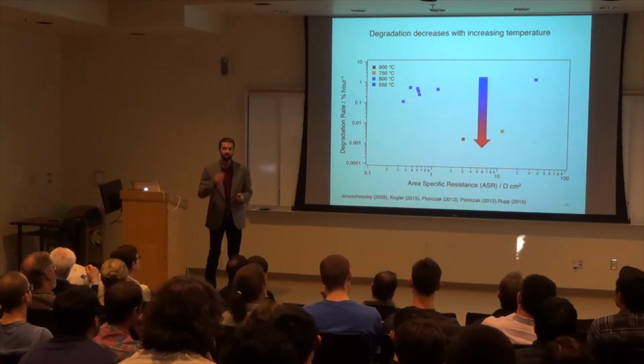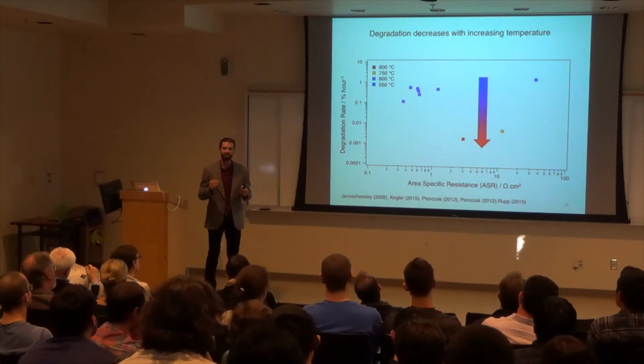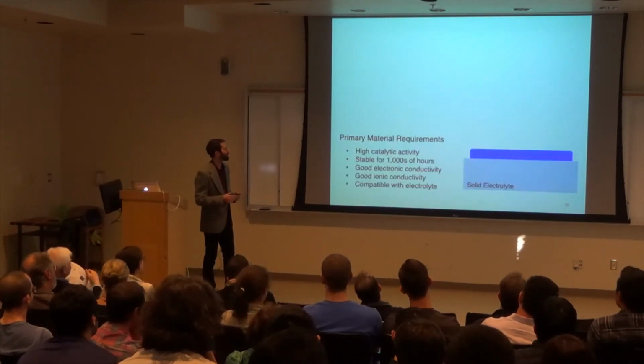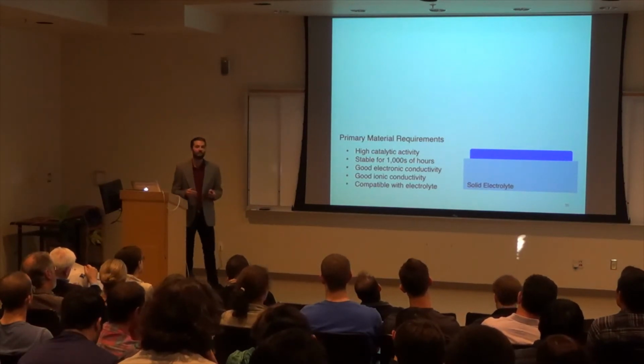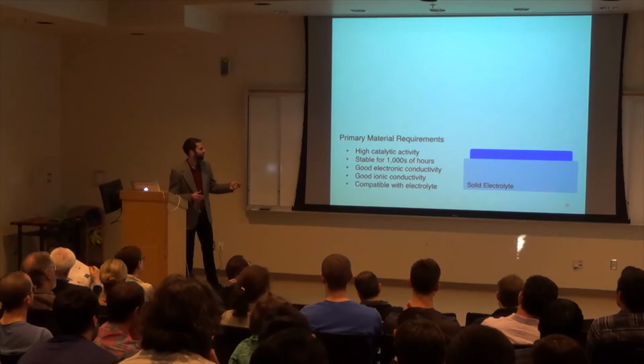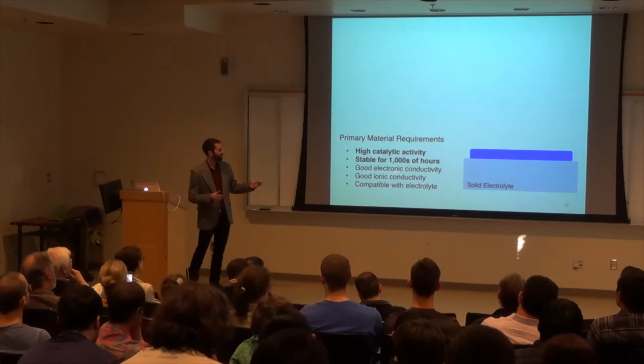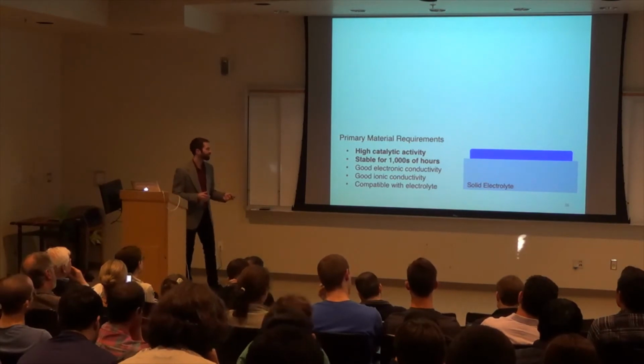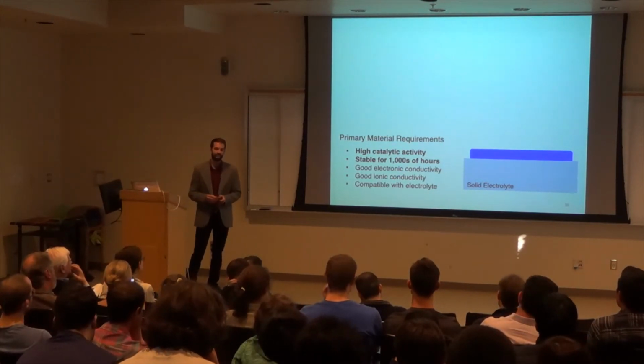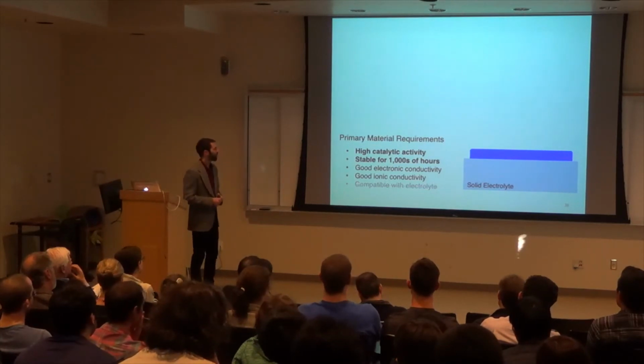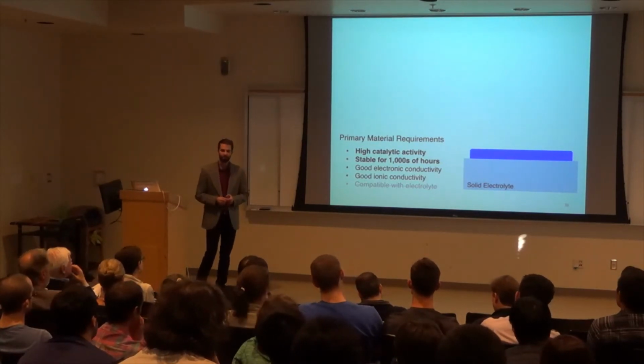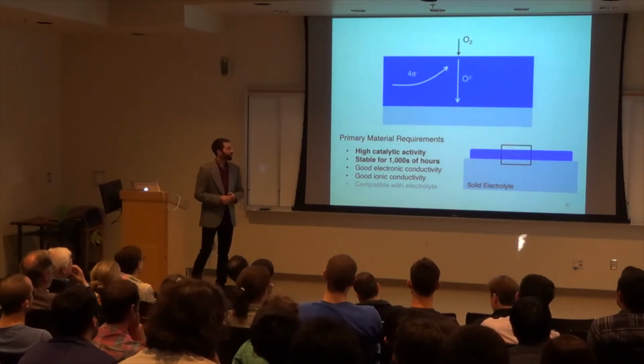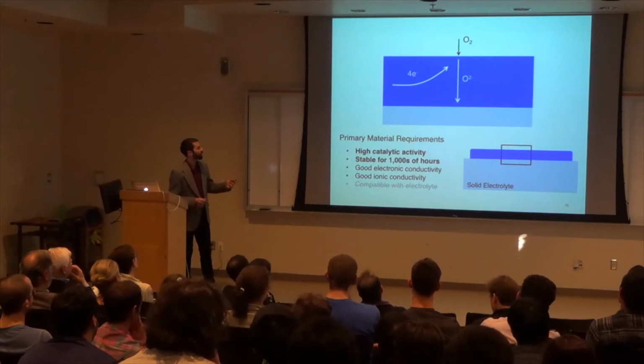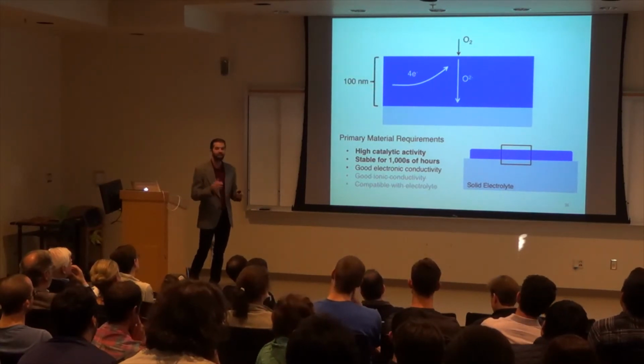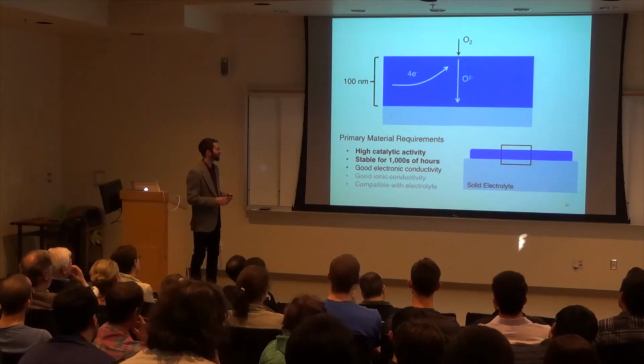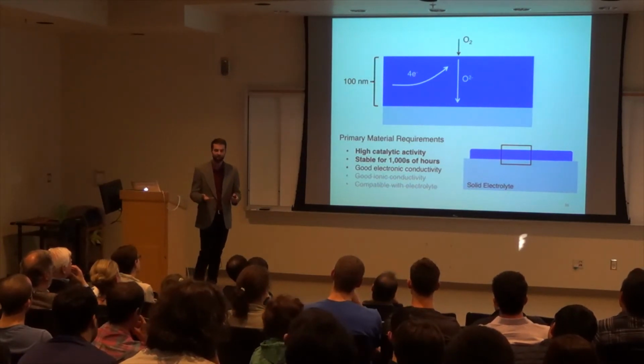Now, in order to test our materials and make sure that we understand exactly what's going on at the surface, we need to essentially engineer our measurements so that we don't have any convolution from everything down below. Electronic conductivity, ionic conductivity, compatibility with the electrolyte. So these are the things we want to focus on. Activity and stability. We've already selected electrodes carefully, so this is not a problem. For ionic conductivity, if you look at the thickness of the films that we're working with, they're only about 100 or 200 nanometers thick, which is not a lot of distance for the ions to travel down to the electrolyte. So we can already say that this is not going to be a rate-limiting step in the reaction or convoluting.